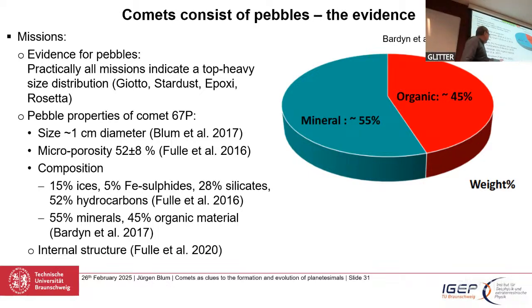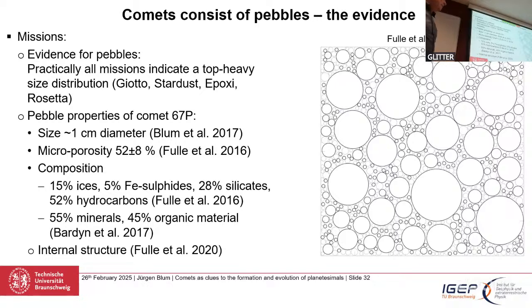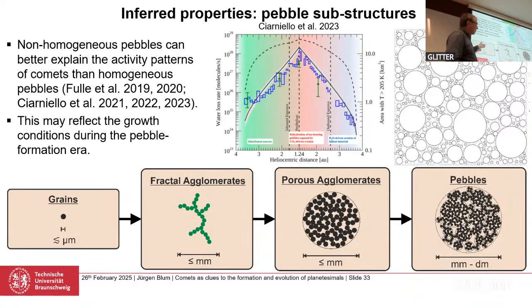And Marco Fulle et al. also argued that these pebbles must have some internal structure, consisting not only of micron-sized particles but of aggregates of micron-sized particles. So here are the particles, here are small aggregates, large aggregates, because only those internal structures, like shown in this plot, can explain the measurements, which are the boxes, of the water emission from the comet. And here's the model that explains that, from Ciarniello et al. 2023. But that is completely under debate: whether that internal structure is really true or not.